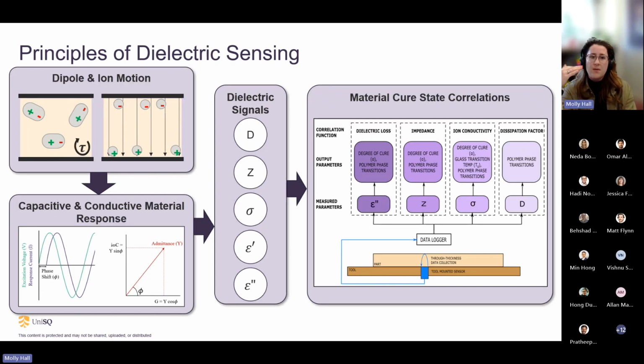So with this monitoring of the dipole and ion motion, we develop a phase shift between the application of that voltage, which causes that electric field, and then the response current, which leads to a material admittance. The material admittance is a ratio of your conductive response and your capacitive response of your material. And from this admittance, there are several different dielectric signals that you can actually use to monitor your process. So we have our dissipation factor, impedance, ion conductivity, permittivity, and loss factor. So 5 different signals all relating to the same behavior that's going on.